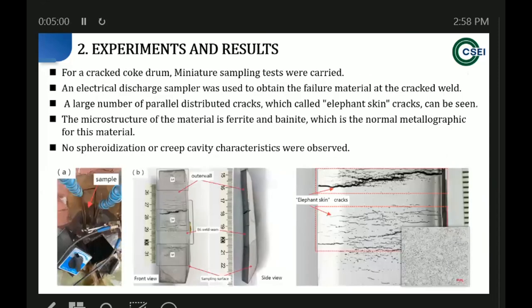And we also did some mechanical property tests, and this is case 1. This is a cracked coke drum, a very serious crack, with through wall cracks. We took the sample from the failure material at the cracked weld, and we can see the elephant skin cracks here. The microstructure of the material is normal, and we didn't observe spheroidization or creep cavity characteristics.